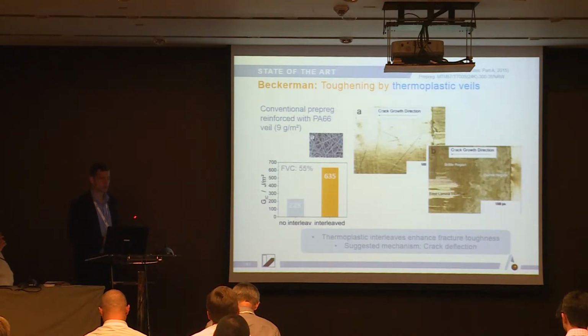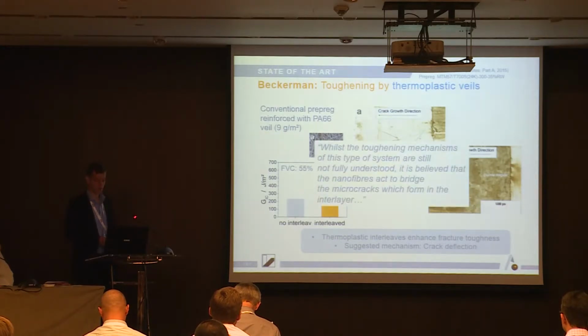Another mechanism is to use thermoplastic veils, so to use a conventional prepreg, which is just reinforced with a veil. So you have different layers of your prepreg and your resin. You can see that there's also a very huge increase in the fracture toughness of this material.